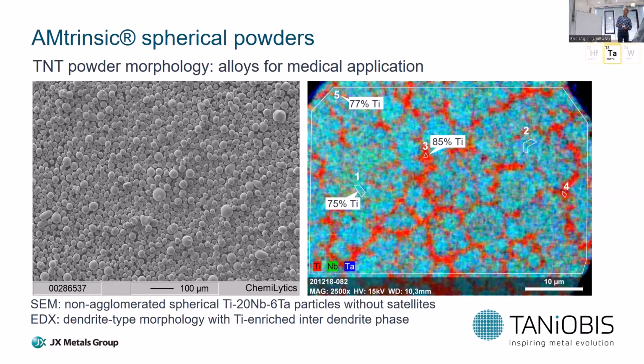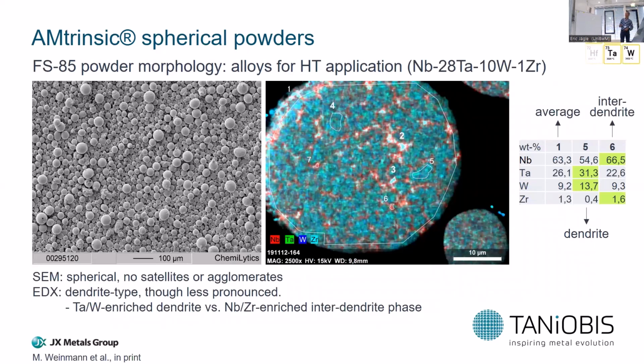Here this is a ternary alloy, a titanium niobium tantalum powder. Here you can see spot 5 is the overall composition of the particle, containing 77% of titanium. Remarkably, those powders do not form very homogeneous microstructures. There is a slight elemental demixing observed with dendrite type features. The dendrite type structures are blue, shown here, enriched in niobium and tantalum, and the interdendrite phase is enriched in titanium. So this interdendrite phase is composed of 85% of titanium, and the interdendrite phase is accordingly composed of 75% of titanium.